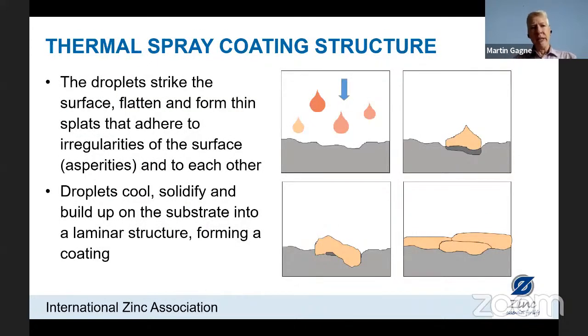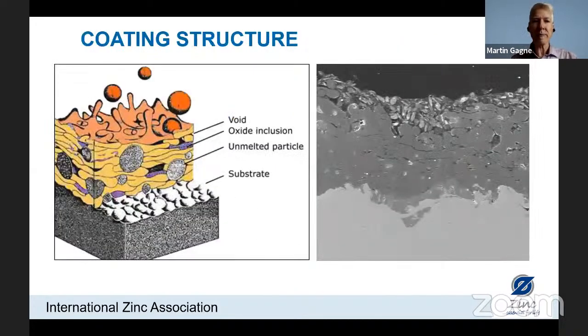So the thermal spray coating structure, these droplets are impacting on the surface, they flatten, and they also leave irregularities on their surface, which helps anchor the next layer of drops that land on the top surface. And this is how we build up the coating. And the coating thickness is really dependent on the time of spray.